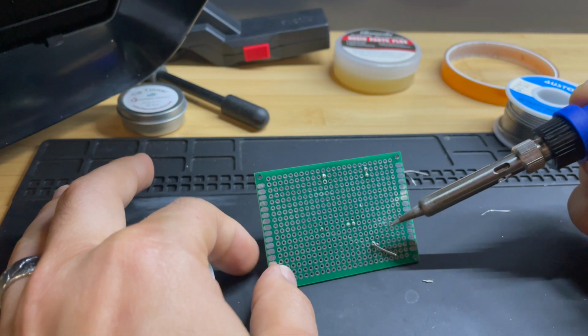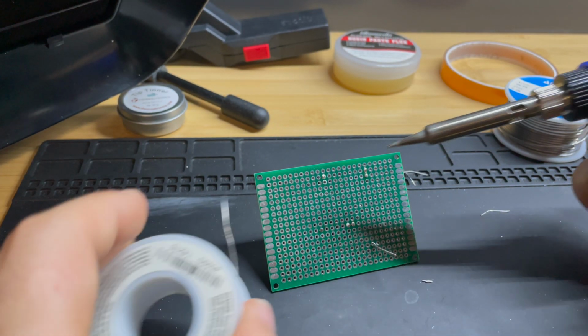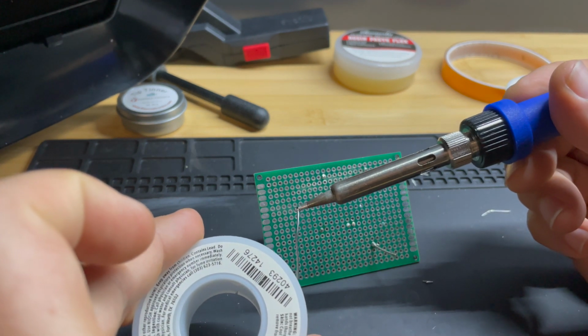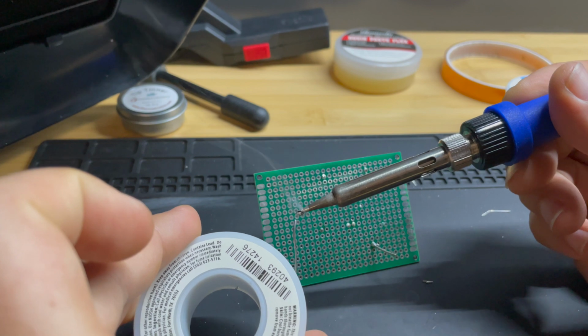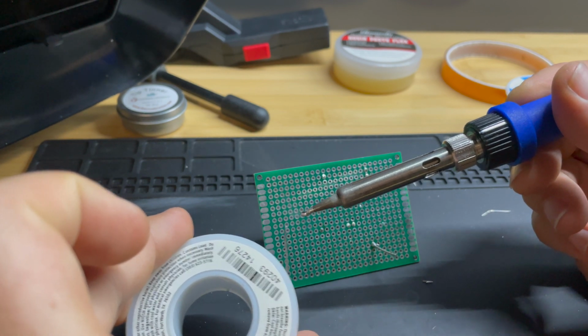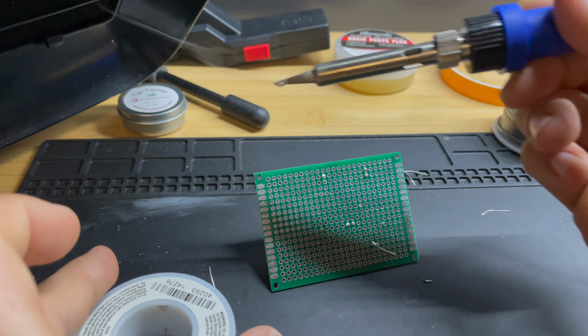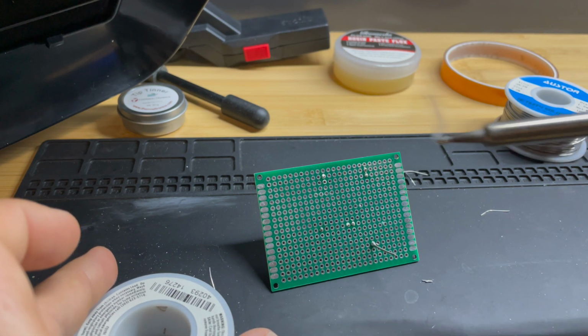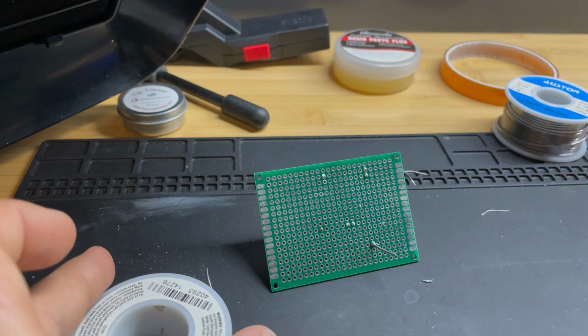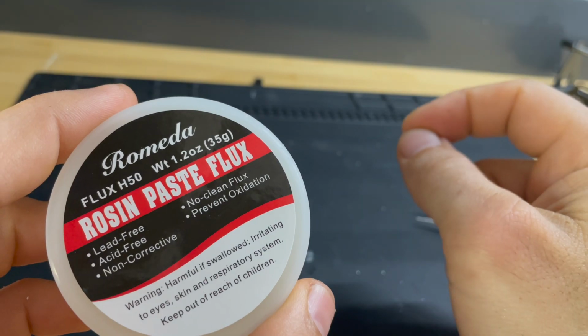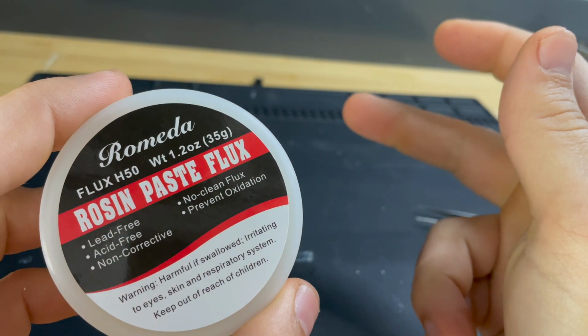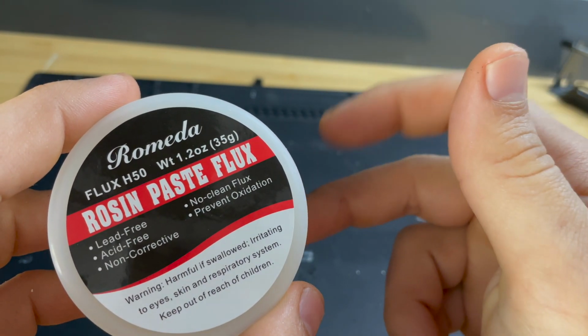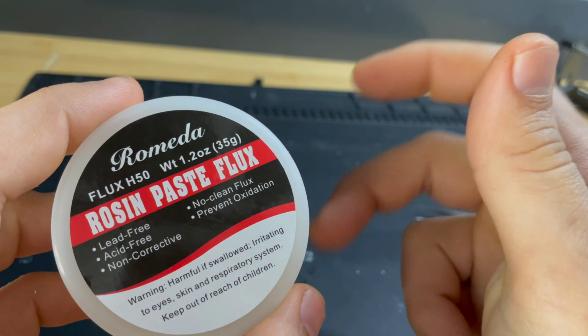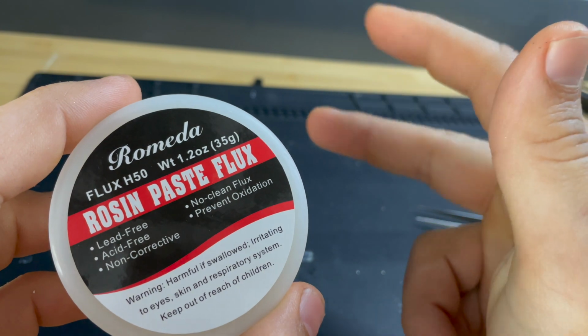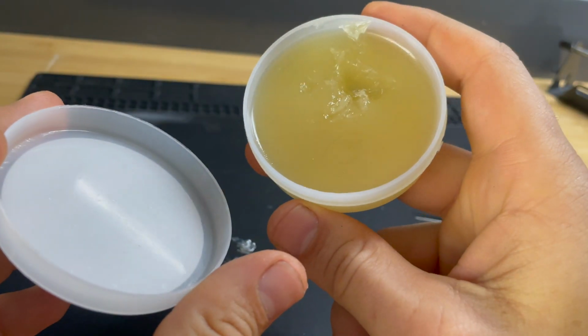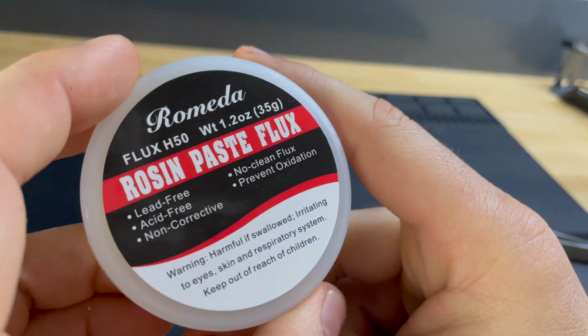So as you use your solder, as you're soldering, that flux is going to attack oxidation on the metals that you're soldering onto. Now, as you do that, you're burning off the flux, and the fumes you see, the smoke you see when you're soldering, is actually the fumes from the rosin flux. And that stuff is kind of hazardous, so you don't want to breathe that in. You want to avoid that as much as possible. But as you solder, you're burning off flux, and that's removing oxidation. And if you are soldering the same place or using the same solder for too long, you can burn off all the flux. Or if you're doing rework and you're trying to remove some oxidation, you may want to have a little extra flux around to add back into the soldering process.